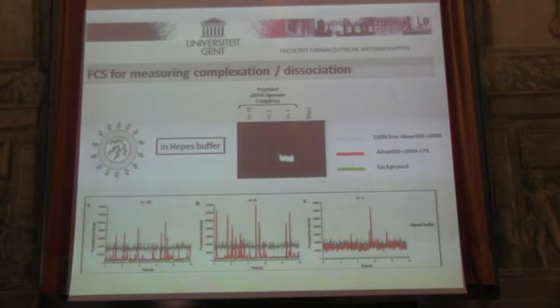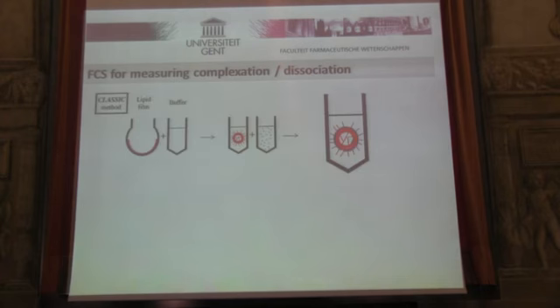And the same was measured with this FCS technique. So this is the 1:1 result. And indeed, the gray signal is the free siRNA. And if you add this little amount of liposomes, indeed you see only a very tiny amount of decrease of the background line, because only very little siRNA is complexed, and very few peaks indeed. But if you include more liposomes, then you see a bigger drop of this baseline, because more siRNA is included, and you see more peaks happening. So this nicely corresponds to what we see in a gel electrophoresis experiment.